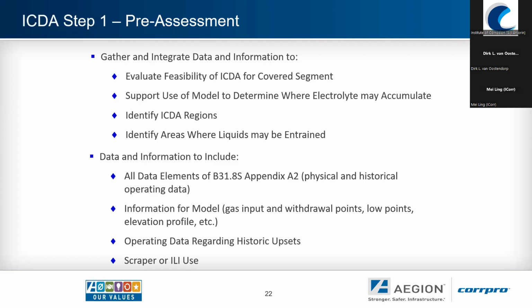Data information, important pieces here. All the data elements that are considered by ASME B31.8S, the physical and historical operating parameters must be available for inclusion in this information for the model. So if we're thinking about running a flow model to do these calculations, typically we would use something like Olga in order to make this sensible. There's quite a list of important pieces of information, such as the flow rates, the pressures, the temperatures of the flow, the chemical composition, all of these pieces together, along with detailed information on the elevation profile of the pipeline that allows us to look at the low points and actually do the critical angle assessment.